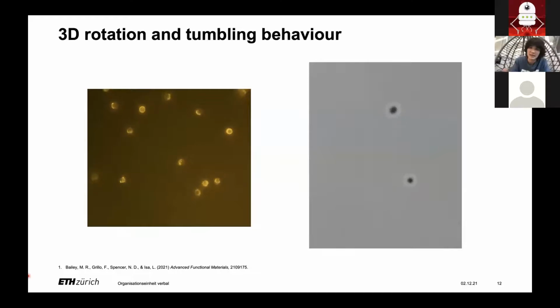However, this still doesn't explain why we observe a 3D motion and not just the 2D state. We propose that there are two contributing factors. The first is we just looked at the passive system, so no UV light, they're just diffusing. And what we see is that the particle is freely diffusing. It's got free rotation in 3 dimensions. And we expect that because of the lightness of the titanium cap, so we don't have a dense film, we have nanoparticles, agglomerate structures, the particle doesn't have a bottom heaviness to the same extent that other systems might have, which allows it to rotate better in 3D.